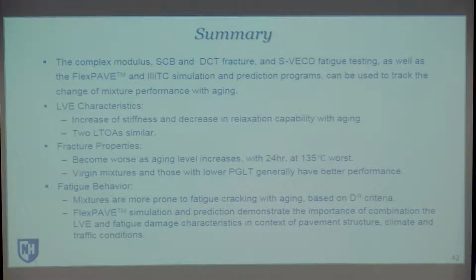For fracture properties and fatigue properties, again, you've got to be careful what's happening with those longer term aging levels. You're getting differences in the properties that you're measuring at those two different conditioning procedures, and it's not consistent. We can't say that one is always more conservative than the other. It changes from mix to mix, and it's also changing whether you're looking at the fatigue approach, the fracture approach, and what test temperature you're evaluating. So that comes back to what's most representative of what we see in terms of changes in the field, and that's part of what we're looking at moving into the future.